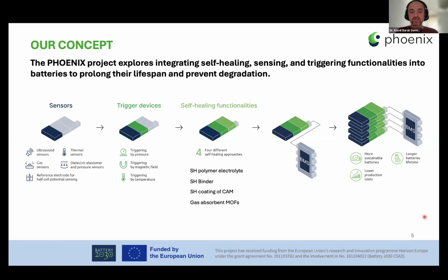When it comes to the self-healing functionalities, we have 4 different self-healing approaches. We are trying to equip the self-healing by polymer electrolytes, by binders, by coating on the cathode active materials, or by gas absorbent separators from metal organic frameworks. Once all of that has been combined, proper communication between the BMSs should be provided. That will allow us to detect the degradation and to take the necessary actions to avoid that.